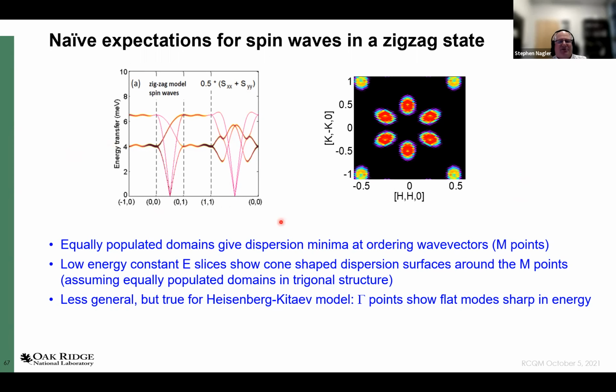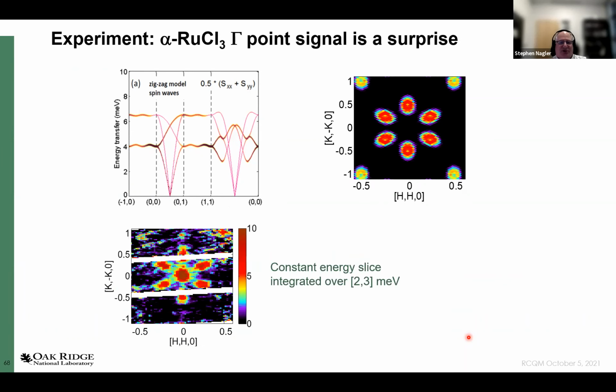The details of what happens everywhere in the zone depend on the details of the Hamiltonian. For the Heisenberg-Kitaev model, these gamma points are basically flat modes that are sharp in energy, just in spin waves. Now, if I look at alpha ruthenium trichloride and I do a measurement like this, here's what I see. I do see these spin wave cones at low temperature. I also see this other piece of scattering at low energies centered around the gamma point, right? Which we didn't necessarily expect from ordinary spin waves.